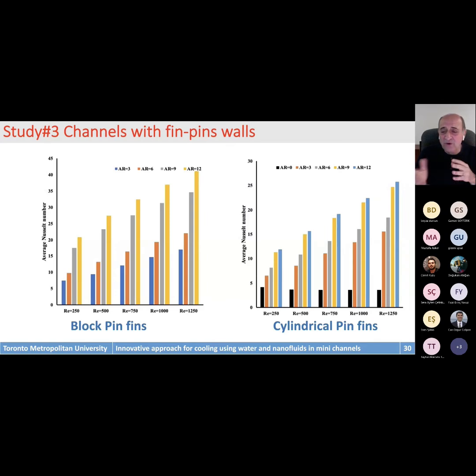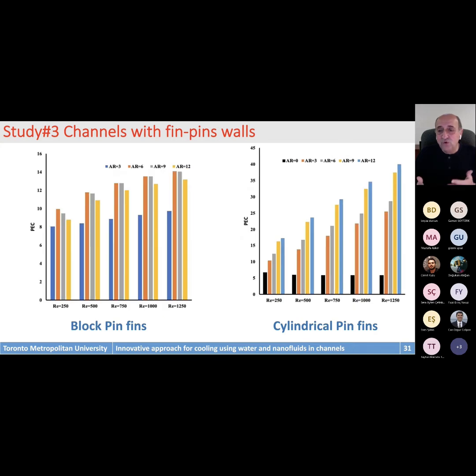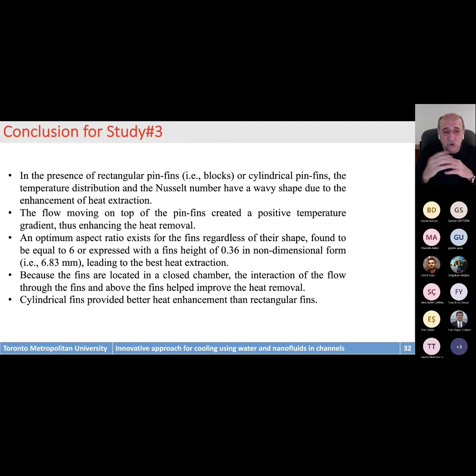And when you look at the average Nusselt number, you see, of course, the better performance is when the aspect ratio is 12, meaning the fins are at full height, but they still have a little bit of escape from the top for the flow to penetrate. But when you do the performance evaluation criteria, we notice that the block pin fin is doing a good performance, but not as good as the cylindrical pin fin. And the reason for that is the friction factor in the cylindrical pin fin is less. So this is the finding.